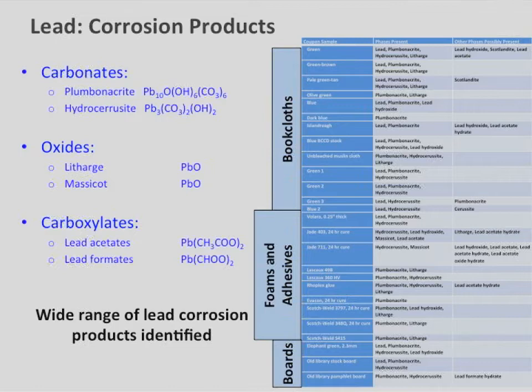What we see in there is a lot of plumbonacrite and hydrocerussite carbonates. We see a little bit of oxides, litharge and massicot, and not very many carboxylates, which is somewhat surprising—I think there's 1 or 2 samples with acetates and 1 or so with formates. If I was going to keep one metal coupon in the Oddy test, it would be the lead coupon.